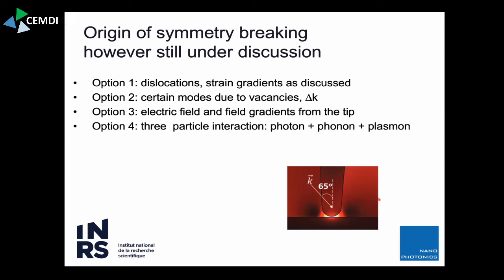The effect that we believe is probably relevant is that when you do this experiment with this gold tip and the optical near field, you get huge electric fields. And these electric fields introduce very high gradients, but even on the scale of a chemical bond, the electric fields are substantial. So these electric fields could very well break the symmetry of a molecule or of a bond, because they are amplified near field electrical fields. And that means that something which was symmetry prohibited before could very well become activated in the presence of a very strong local electric field. So it's like changing the symmetry of your molecule under an applied electric field, or changing the symmetry of your crystal under an applied electric field.